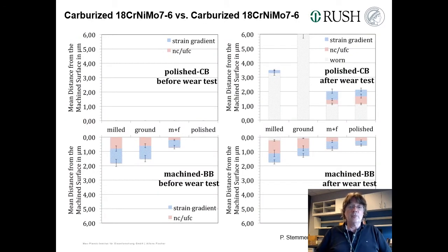The polished pins, this is the surface of the polished pins here at the zero level, meaning they were polished to perfection in the laboratory. There were no strains at all below the surface, while after milling on the base body here, you have this severe plastic deformed material, which is the red color, and below that you have a strain gradient, and here is the base material. So after wear, you find in the base body similar things.